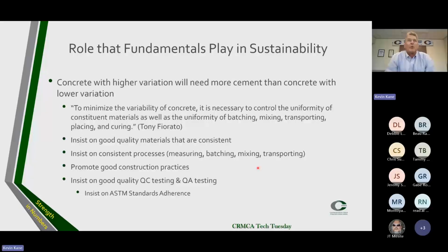So let's talk about the role that fundamentals play in sustainability. It's kind of hard to get around this, but concrete with higher variation with respect to compressive strength performance will need more cement than concrete with lower variation. And from the ASTM C917 report, Tony Fiorato wrote, to minimize the variability of concrete, it is necessary to control the uniformity of constituent materials as well as the uniformity of batching, mixing, transporting, placing, and curing. Tony Fiorato is a pretty smart guy. He pretty much nailed it. If you want low variability in concrete, you've got to control the uniformity of your materials and your processes.